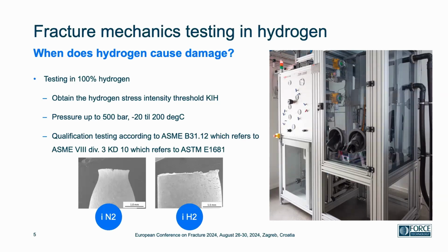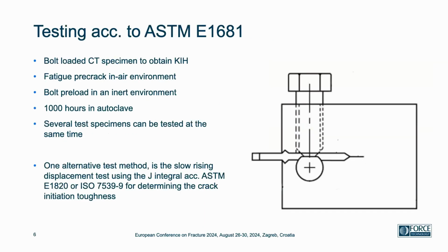This test method is the qualification testing according to ASME B31.12, which is the hydrogen pipeline standard in the ASME code. And the testing refers to the ASME Boiler and Pressure Vessel Code, Division 3 KD-10, which then refers to the test method in the ASTM E1681. One of the test methods in the ASTM E1681 is the bolt-loaded CT specimen to obtain the stress intensity threshold factor K_IH.